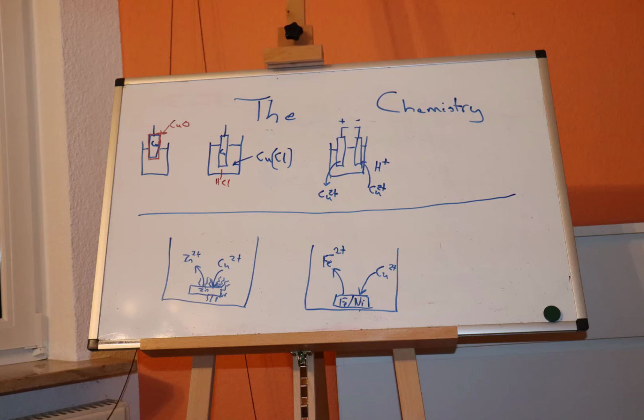If we have a better surface, like nickel, we can coat it entirely with copper, but nickel doesn't dissolve in the solution, so we also need to have some iron in there, and that's where the fineness of the stainless steel comes in. If the stainless steel is too good, none of the iron will dissolve and it won't work, or if it's been heat treated. If the stainless steel is too bad, then there's too much iron in it and it won't work either. Just right means we end up with a copper layer on the top. Unfortunately, I can't tell you what that is because it was a piece of stainless steel that I found in my house.